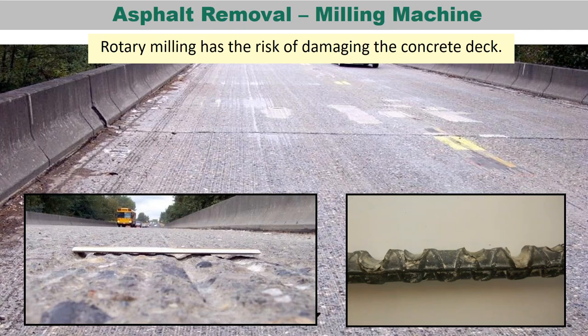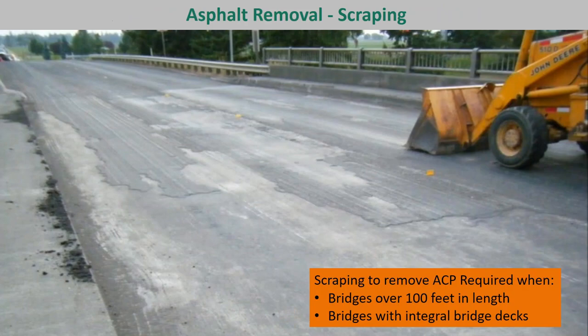So here's another picture of if the rebar was close to the surface, the planers could damage the rebar, leave thick grooves in the bridge deck. So what we're requiring now is that bridges that are structural decks over 100 feet in length with integral bridge decks, we're requiring the contractor to scrape off the asphalt instead of grind it off with the rotomill.